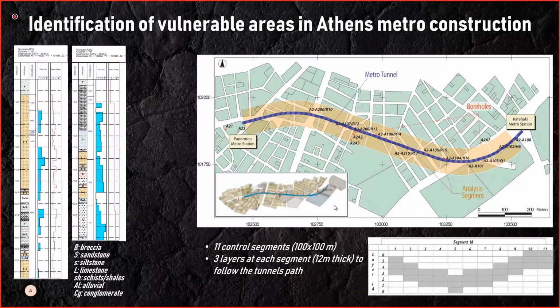The data that we have come from 16 boreholes, and that actually identified almost 36 lithological types. In the 2 borehole logs on the left, you can see the data types that we had. This is lithology, RQD, MR. MR is actually an RMR derivative, especially designed to cater for poor ground conditions, that the Athens Metro design team used, weathering degree, and also some laboratory tests at specific points. In order to proceed with the analysis, we first tried to reduce these 35 lithological formations to 8 main geological units, which are breccia, sandstone, siltstone, limestone, schists and shales, alluvial, conglomerate materials and fracturing zone.